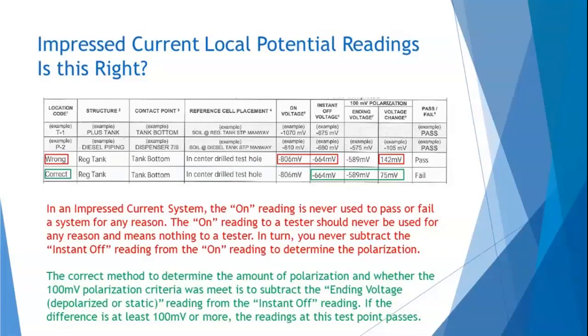So as my example here, in the first regular tank bottom drilled test hole in the center, we had 806 on and 664 off. Well, that's 142 millivolts, but you're using the wrong numbers to determine the 100 millivolt polarization. You must use the instant off reading minus the ending voltage, which is defined as the static or depolarized reading. So in our example here, if the first line, you used the first numbers to determine pass or fail, you would say pass, but that's incorrect. The second line is showing the correct method, and that system, or at least that tank or pipe or whatever we're testing, would fail. So make sure you use the correct numbers.